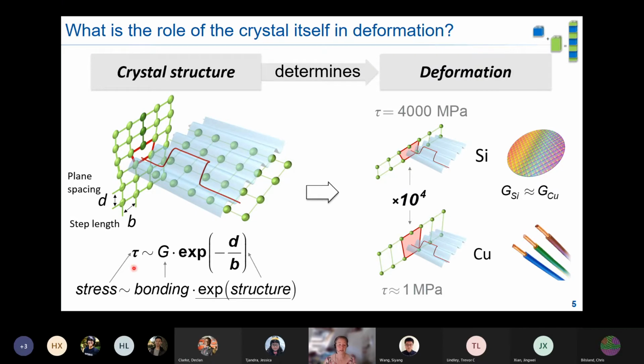And that depends actually exponentially on the distance between the slip planes over the Burgers vector, so the jump distance of a dislocation. The bonding, the shear modulus, goes in as well, of course, but it goes in linearly. So it's not as strong an effect on the absolute stress that we are measuring in a material. So what does that mean?